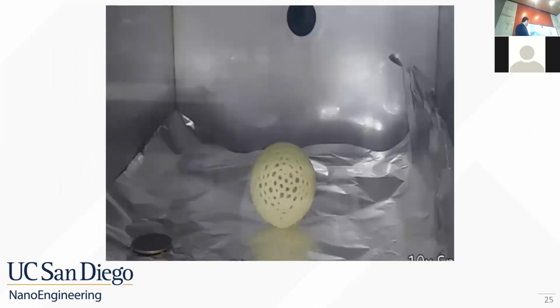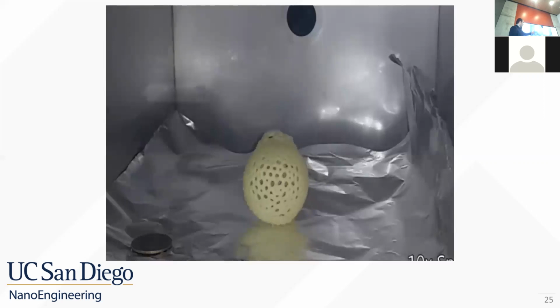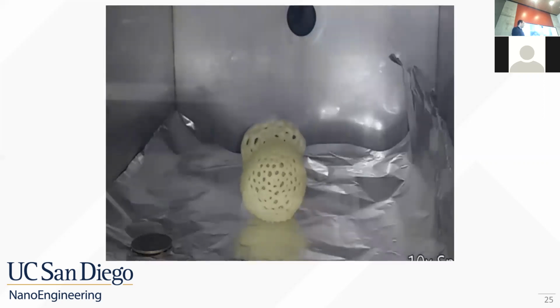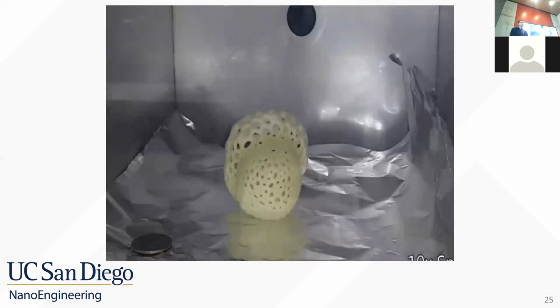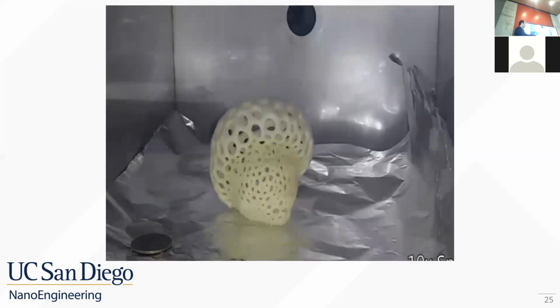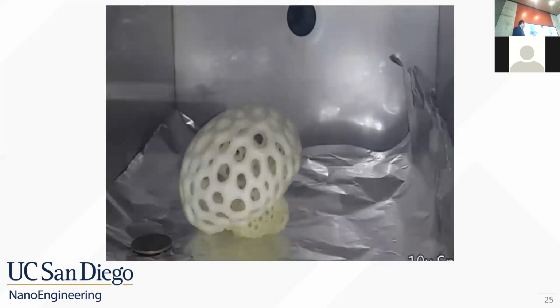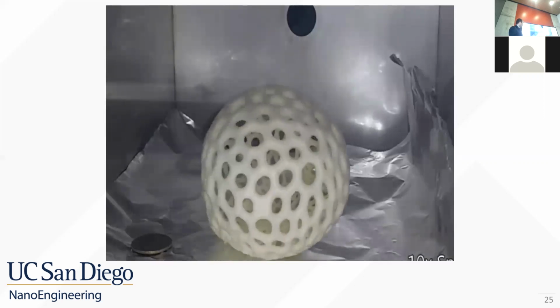Here's a video of one of these polymer spheres expanding. You can see that an expansion front starts on the part, and because the decomposition of Boc anhydride is an exothermic process, this expansion front propagates until the entire part has reached its final resultant size.